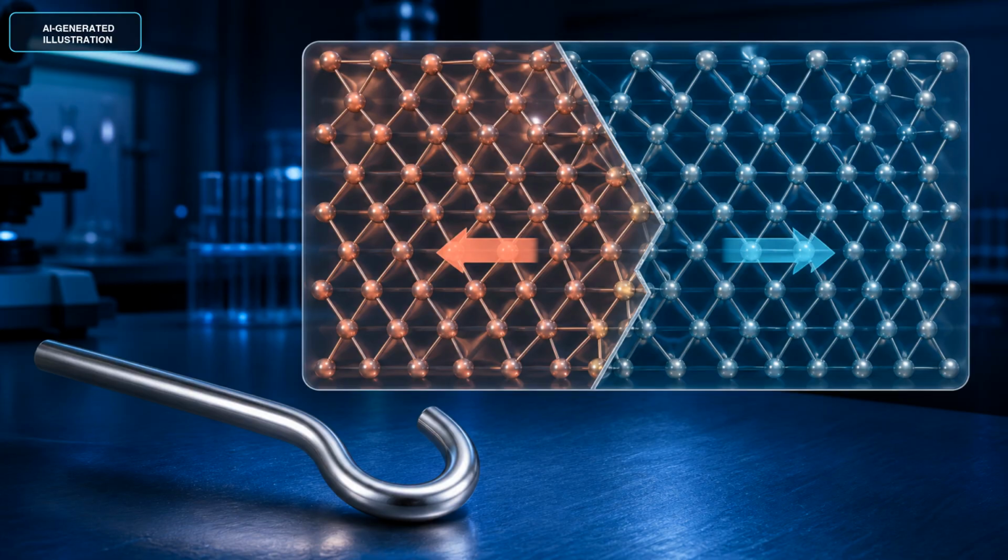Martensite can form in several twin-related variants. Imagine two tiny shears that point in opposite directions. They make room for the new crystal locally, but they also accommodate one another, so the whole wire keeps almost the same visible shape. The crystal has changed, the ruler-level shape has not. That paired, self-accommodated state is twinned martensite.